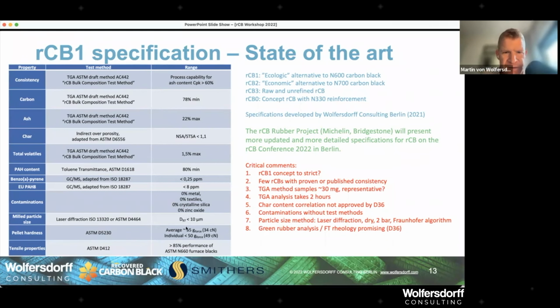And the D97, to repeat, this is the spherical material corresponding to 97% smaller than 10 micron. Nowadays, I would say maybe it's a bit harsh. There's maybe 20 micron is good enough. The problem I have nowadays with the D97 is it means 3% can be above 10 micron, and that 3% can be anything above. They could be 100 micron, and that is a risk. So, which is why I tend to think, although the D99 has a higher error in the determination, I like more only to have 1% open than 3% open. So much about the 10 microns and the particle size measurement.